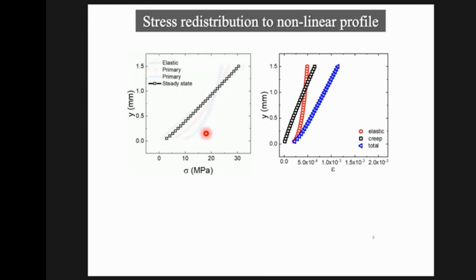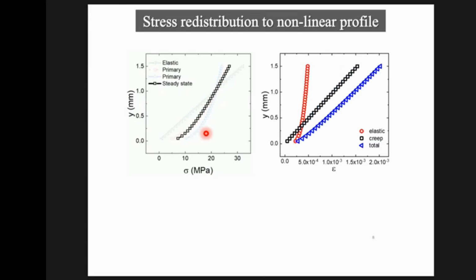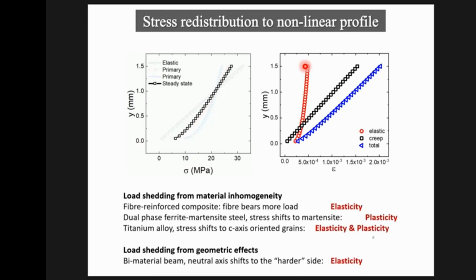So if you think about it, this is the same phenomenon that you have. By the time you've reached a large creep strain, where you can neglect the elastic part, your total strain is more or less your creep strain. But the distribution of elastic strain actually tells you the stress. So the stress distribution, of course, is proportional to the elastic strain. Now, this is a very familiar phenomenon. There's nothing very mysterious in all this.